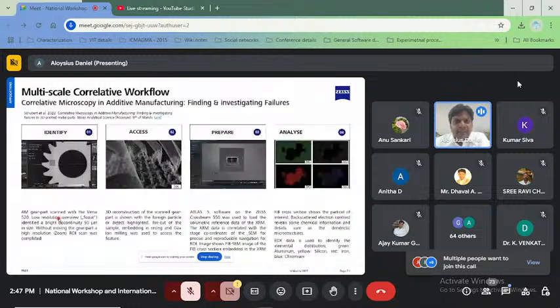And the next example is additive manufacturing, one of the hot topics even in India. So here you can see a gear component which is manufactured through metal 3D printing, additive manufacturing. But there are lots and lots of challenges when you go for additive manufacturing, starting with dimensional accuracy, because there is always a shrinkage factor that comes into the picture, and when you try to anneal the sample for improving its tensile property. So starting with the dimensional accuracies, to the internal unsintered particles, contaminations, foreign particles, voids, cracks. Lots and lots of challenges are there when you do additive manufacturing through 3D printing.